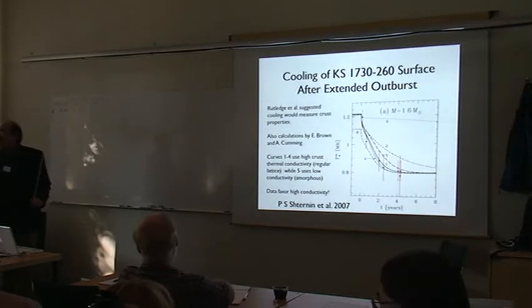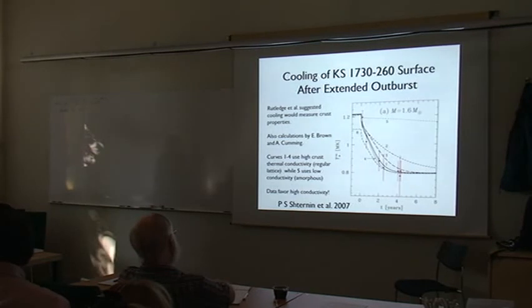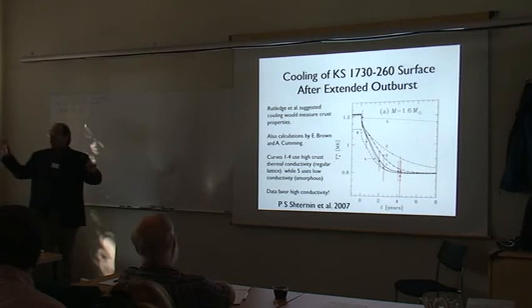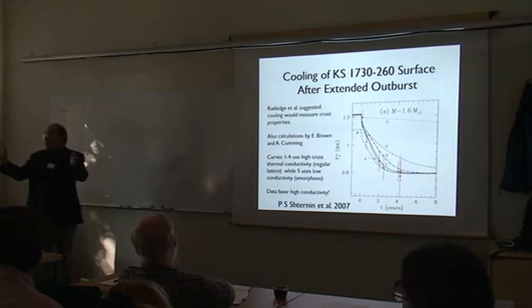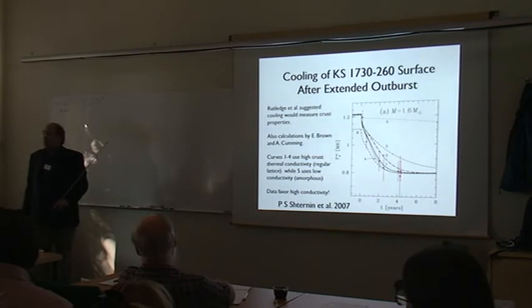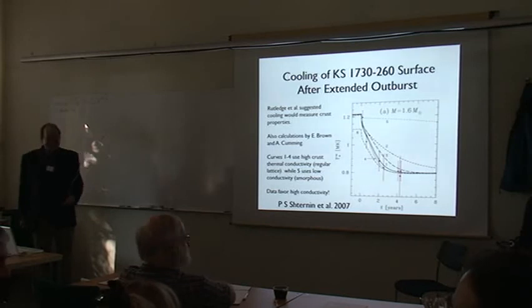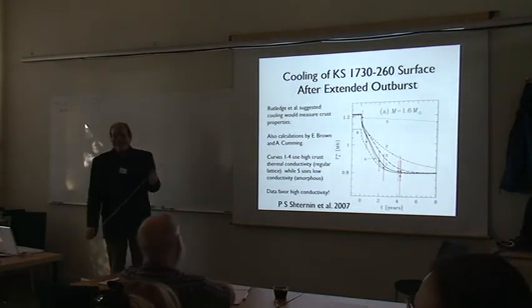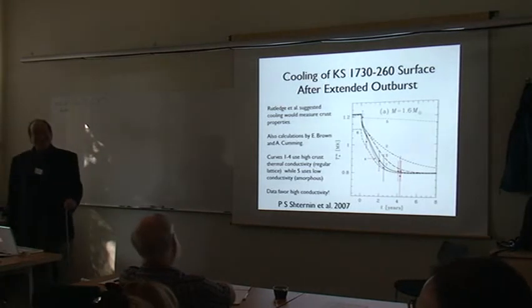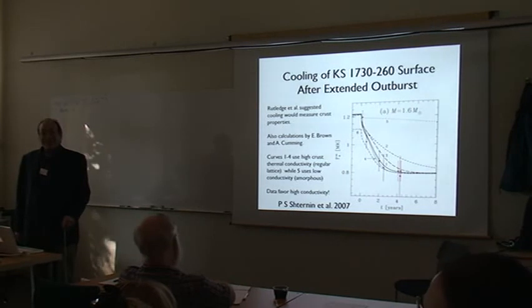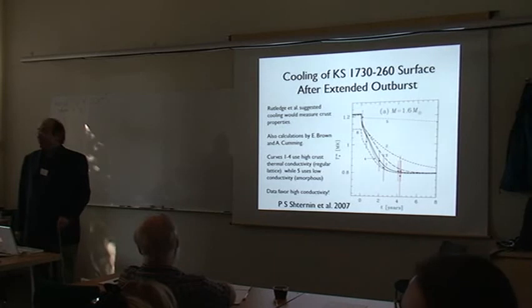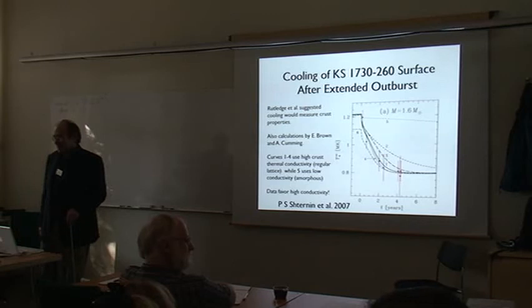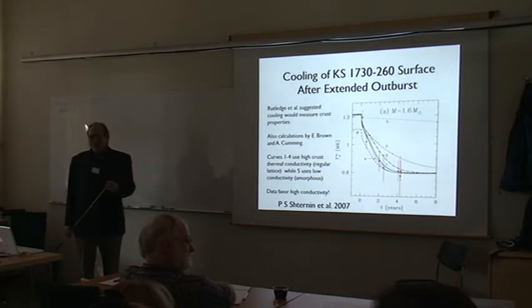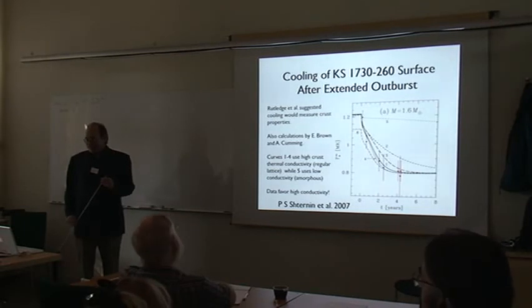Is this assuming spherically symmetric accretion? Do these calculations assume that the accretion is over the whole surface of the star? They assume basically that the star was uniform to begin with, and then the accretion stopped, and they're just letting it cool. Is that reasonable if you have accretion around an equatorial belt? That's a big can of worms - I would assume the matter would flow toward the pole. At the surface it makes a difference, but when you look at density much higher, even if you have a boundary layer of some kind, it shouldn't give you a massive temperature gradient. You can't make a mountain on the equator, so the matter should flow toward the pole. You couldn't just make a hotter belt without making a mountain - that would have an effect deeper, because the temperature is much higher inside than at the surface.